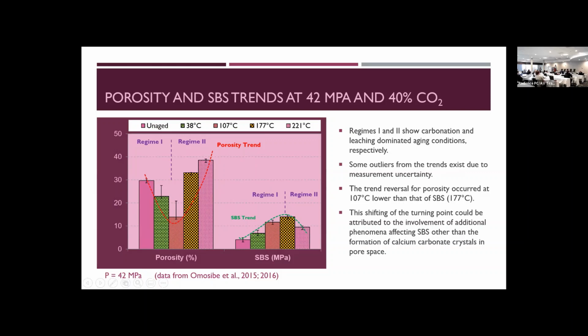And if we compare on the same graph the samples for porosity as well as the samples for shear bonding strength, you can notice that we have a porosity trend with the minimum at around 107 degrees Celsius. And we have another trend on the shear bonding strength with the maximum just around 177 degrees Celsius. So they are basically reversed in tendency. This might again be the fact that the calcium carbonate crystals in the pore space are responsible for that.